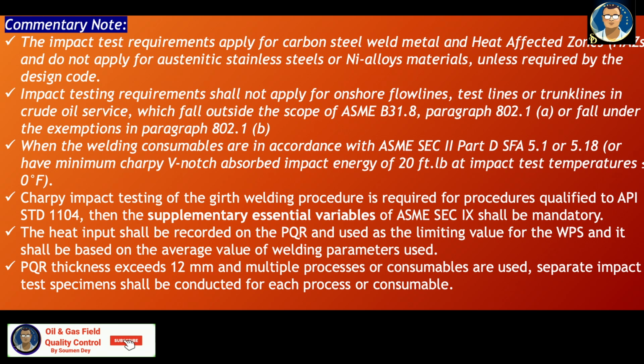Impact testing requirement shall not apply for onshore flow lines, test lines, trunk lines, crude oil service, which fall outside the scope of B31.8. When the welding consumables are in accordance with ASME section 2 part D SFA 5.1 or 5.18, they should have a minimum Charpy V notch absorbed impact energy of 20 foot-pounds at impact temperature less than 0 degree Fahrenheit. Charpy impact testing of the girth welding procedure is required for pipelines qualified with API 1104.